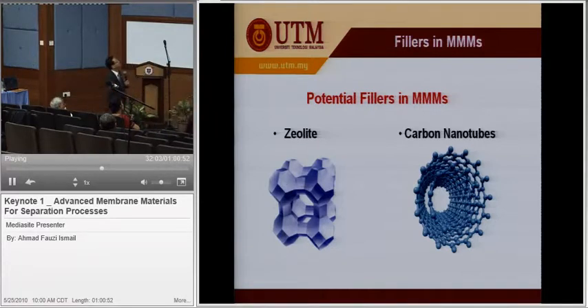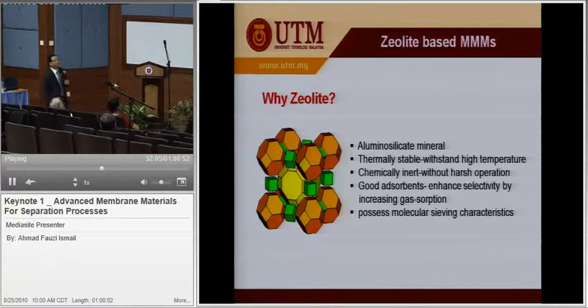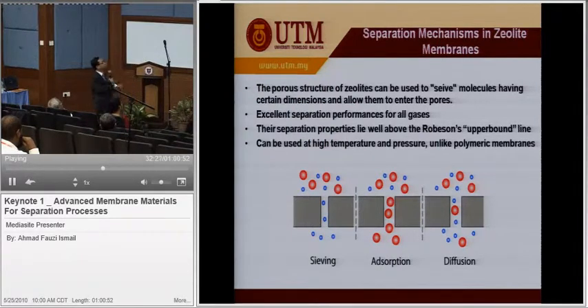Now, zeolite we use because it is thermally stable, withstands high temperature, chemically inert without harsh operation, and possesses molecular sieving characteristic. Molecular sieving characteristic is very important. It's why we use it. And the separation mechanism in zeolite is based on these 3. Some of these mechanisms are undesired. But we can compromise by including polymer. That's how we married these 2.